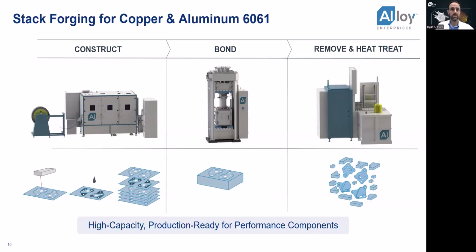After cutting, we print an inhibition agent onto specific surfaces, which prevents bonding in areas where parts need to be separated later. Once the sheets are cut and inhibited, they're stacked in a precise way on a caddy and loaded into our bonding machine. This step uses heat, pressure, and a controlled atmosphere to diffusion bond the sheets together. It's a true metal-metal bond at the atomic level. So there's no brazing, there's no glue, and there's no laminates.